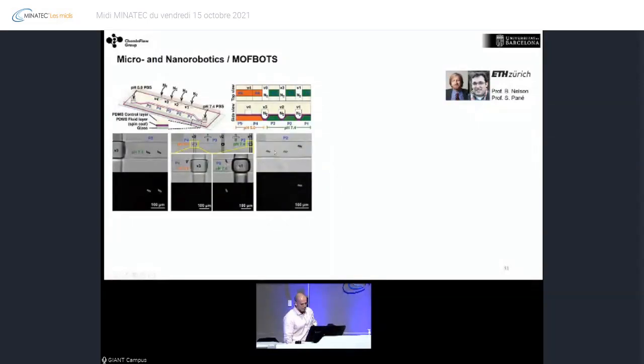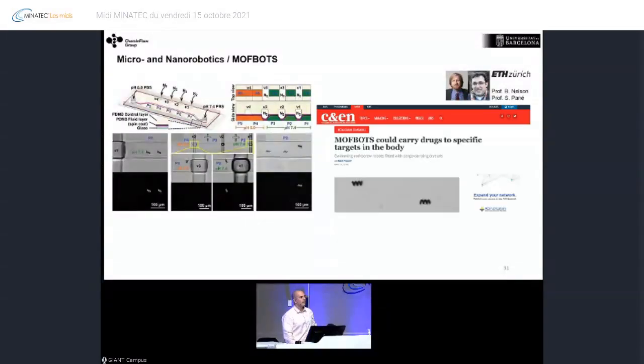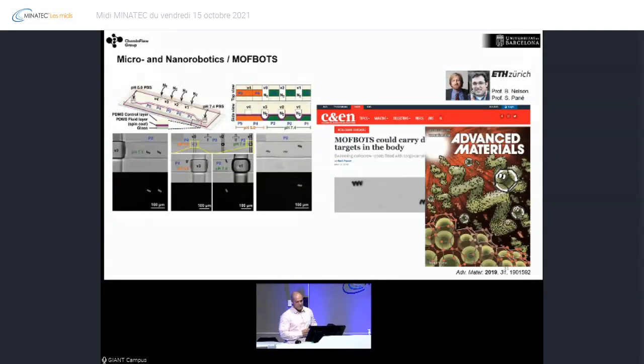And then we can move them backwards to pH 7, where the 2 that stayed there are still fluorescent, but these 2, they lost the cargo because they went to the area that was a lower pH. This had a very big impact in the field. It was highlighted in C&EN. And we also were very happy to do this work in collaboration with the group of Professor Shuhei Furukawa at Kyoto University. This is why we did this cover with manga drawing.